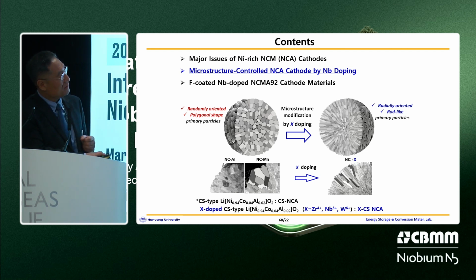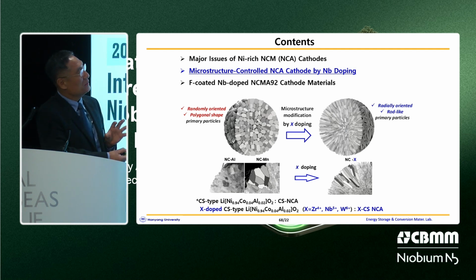As you know very well, conventional NCA and NCM cathodes are composed of randomly oriented, large polygonal-shaped primary particles. This material suffers from huge microcracking during cycling. However, this microstructure can be modified by X doping, especially niobium doping. The modified cathode material is composed of radially aligned long rod-shaped primary particles.